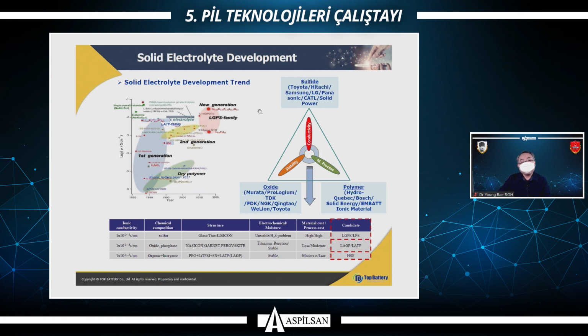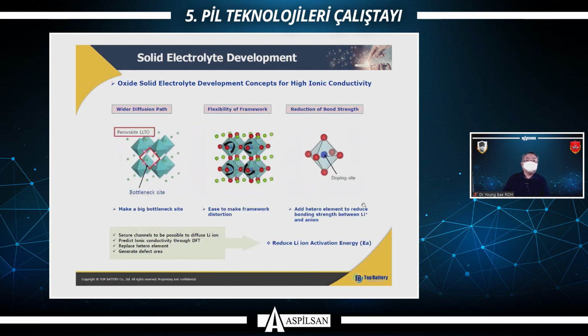And then if you want high productivity, you can research the organic composite polymer electrolyte. Hydro-Quebec, Bosch, and Solid Energy are researching this area. This is one of the solid electrolyte concepts. For high ionic conductivity, we have to reduce the lithium-ion activation energy by securing wider diffusion paths and a more flexible frame structure in the crystal, and by reducing the bonding strength between the lithium ion and anion.